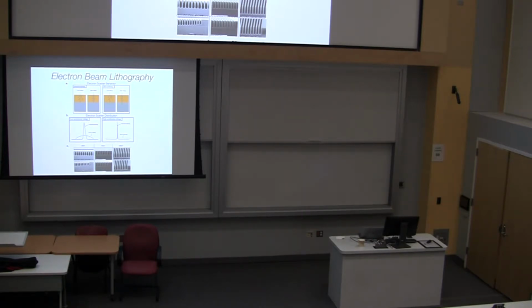For low accelerating voltages, like say 10 or 30 keV, that electron comes in. Most of them go all the way through, but a few scatter. So let's say I only wanted to dose right at this point right here. I would dose along that point, but then there's a whole lot of straggle of all these electrons, and all those electrons will then dose the polymer, break apart their chains, and become soluble. So let's say I tried to make a 10 nanometer line. What I would see is like a 50 or 100 nanometer line.